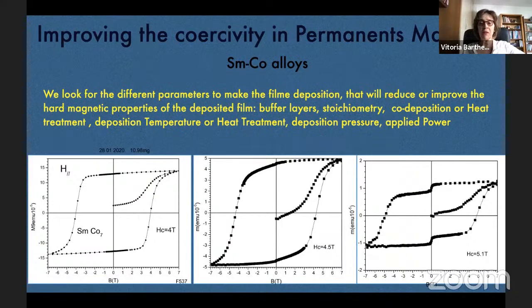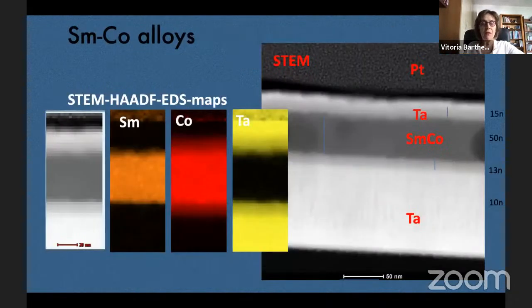When you focus on the buffer layers, and these are the latest results, we are at 5 Tesla in coercivity, and going higher. In fact, we are seeing that the cause of this change is the diffusion of the tantalum buffer layer into the magnetic layer, which causes some pinning in the magnetic layer that prevents the inversion of the magnetization. So we are working on this, and we intend to publish these latest results. Briefly, I can talk more about this.